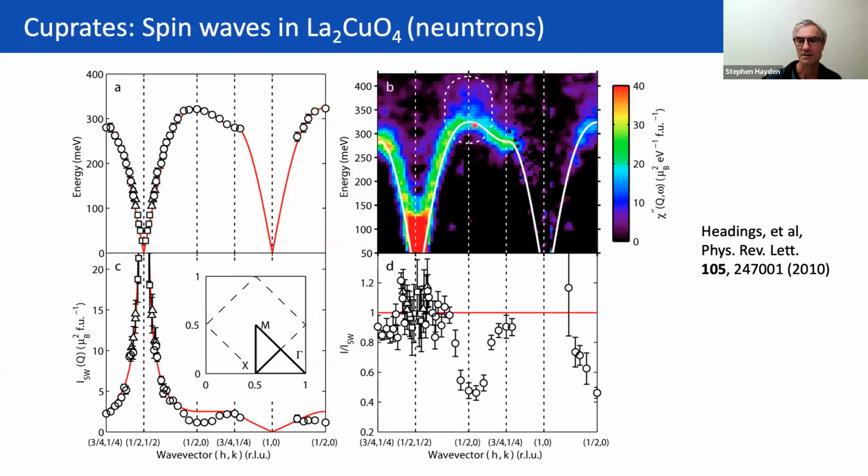They fall apart at a particular point in reciprocal space, the half-half, and they're different along different directions, say along the pi pi or pi 0 directions, or the half-half or half-0 direction. So you have some dispersion between the different directions.